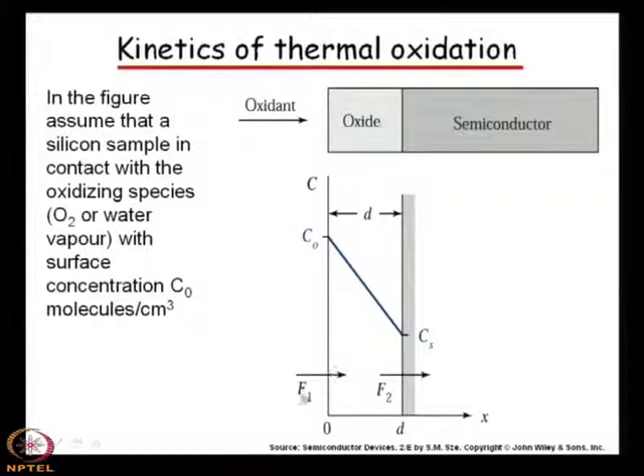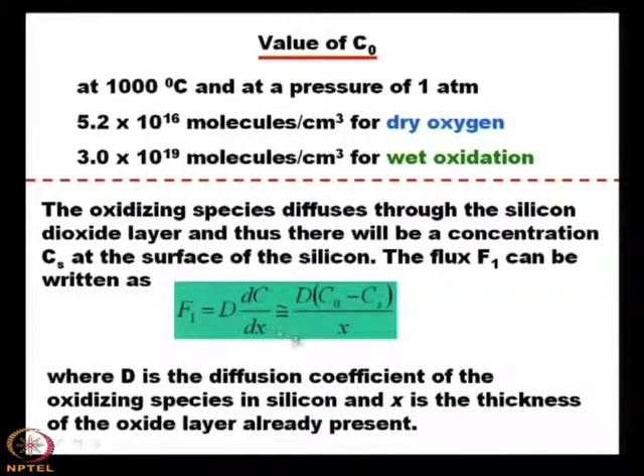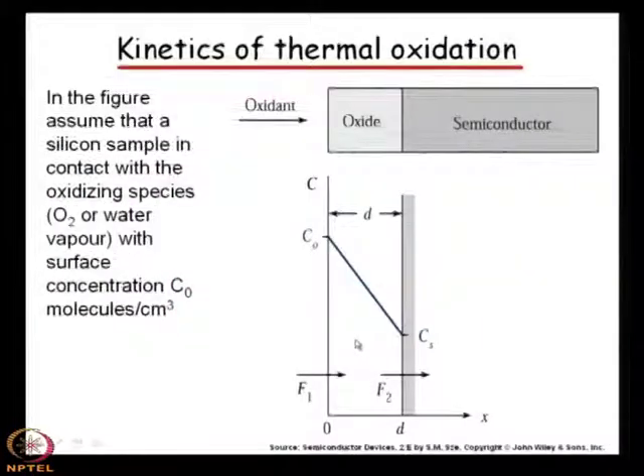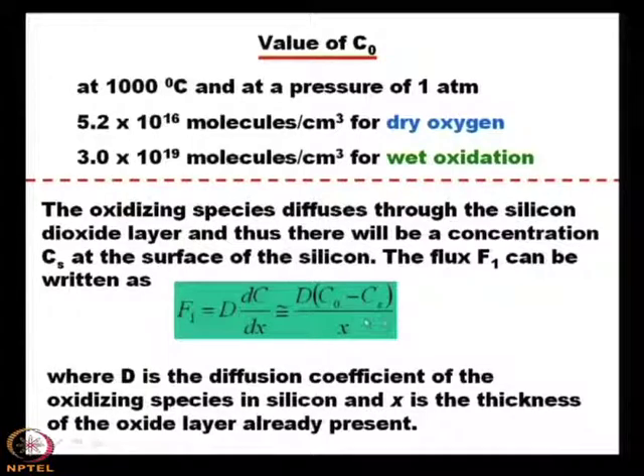Now, we have to calculate the flux at F1, that means between the oxide and the oxidizing species, and also at this surface between the oxide already formed and the semiconductor. So, let us calculate the flux at F1 and F2. If you calculate the flux at F1, that can be written as F1 equals D dC by dx, which equals D into C0 minus Cs by x. Remember that this is the C0 and this is the Cs. So, C0 minus Cs by x is the concentration gradient, because dC by dx is the concentration gradient, where D is the diffusion coefficient of the oxidizing species in silicon and x is the thickness of the oxide layer already present.